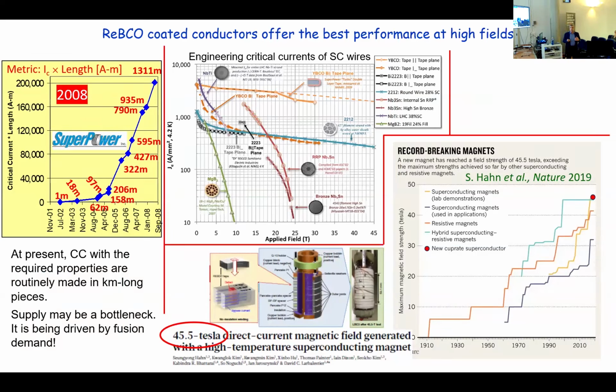Now, the coated conductors, these rare earth REBCO films on flexible metal tapes, offer the best performance at high magnetic fields. This central plot shows the critical current density as a function of applied field for a variety of superconductors. You can see that all the commercial low TC materials, niobium based, collapse at around 25 Tesla, and they become useless above that because you need some finite, significant JC if you want to operate them. The only option are these YBCO coated conductors that can extend up to very, very high fields.